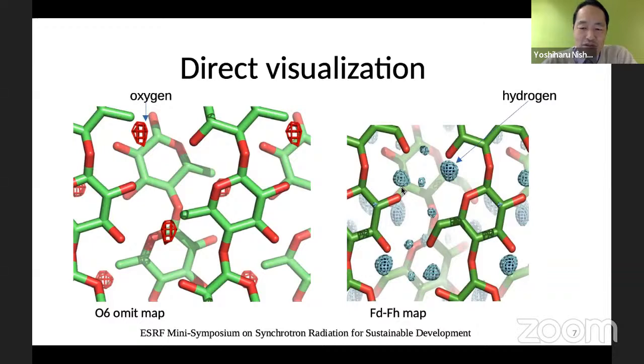And the role of hydrogen bonding was considered to be very important in this structure and property. So here on the left-hand side, this is the X-ray structure where we have left out the oxygen position of this labile oxygen, and where we can clearly locate the position of oxygen. On the right-hand side, we see the neutron data where we can place the hydrogen position thanks to the contrast between the deuterated crystal and hydrogenated crystal.